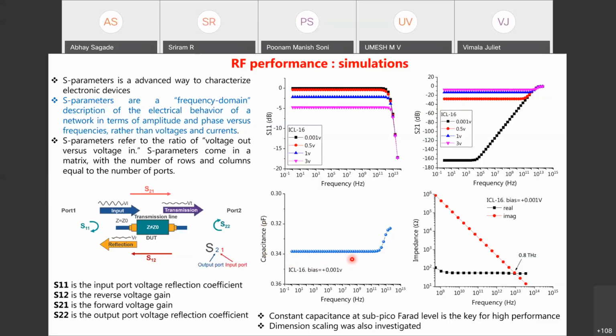To quantify it, you can see that the value of the capacitance is almost 0.34 picofarad. If you look at the capacitance of commercially available diodes, it is in the range of 3 to 10 picofarad. So this capacitance is almost 10 times smaller than that. And as you can see here in the S parameter, this capacitance is almost flat or unchanging up to terahertz frequency. This is the simulated data for intrinsic cutoff frequency, as I mentioned in the previous slide. The black line is the real part, and red is the imaginary part. These two lines cross each other at a frequency of 0.8 terahertz or 800 gigahertz.